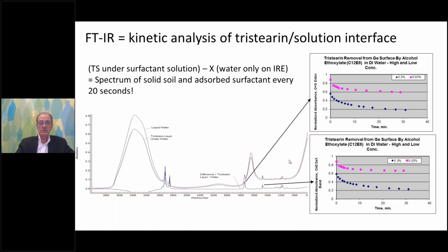The way we get the spectrum of the tristearin alone is, we have our spectra every 20 seconds. Then we go back and subtract the spectrum of water only times some scalar x and obtain the spectra of tristearin and anything else at the IRE surfactant interface. And again, as solubilization occurs and the tristearin is removed from the surface, the intensity of the bands goes down.